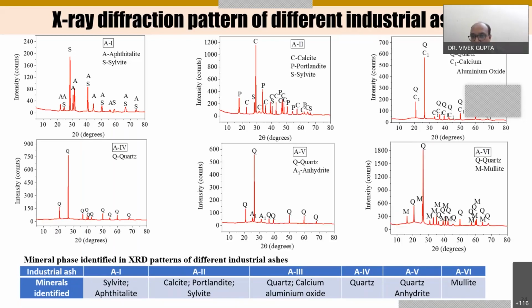One important thing, in the A6, although the LOI is very low, we have found the presence of mullite, and mullite is reported as an inert or non-reactive mineral phase. And this is the major challenge in the power plant ash. Majority of power plant ash have low LOI, but still we are not getting good lime reactivity because of the formation of mullite. So this is another challenge we are facing in the Indian coal ashes.